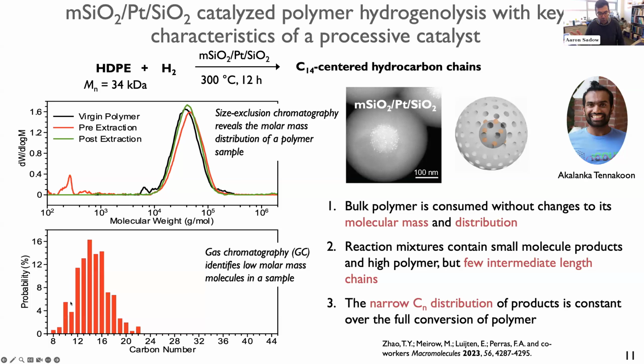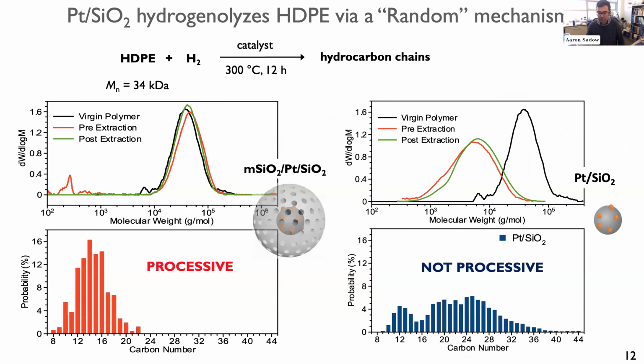So at low conversion of polymer, maybe 5%, we get this kind of distribution, all the way up to some 80 or 90% conversion. So that can be contrasted with platinum on silica, where we've just left the core bare. So we didn't grow the mesoporous silica over top the catalyst. And you see, when you do the cleavage reaction, this is the starting polymer, and necessarily you get the non-processive intermediates from random cleavage.